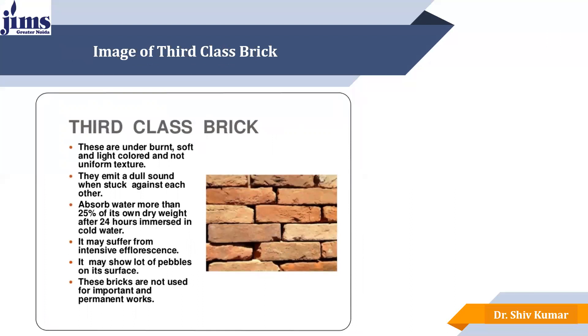Third class bricks are under-burnt, soft and light colored with non-uniform texture. They emit a dull sound when struck together. They absorb more than 25% of water when immersed for 24 hours. These bricks may have efflorescence problems when soaked in water, causing whitish lines or layers to appear on the surface. These bricks are not recommended for permanent works; only temporary structures like labor huts can be made using them.